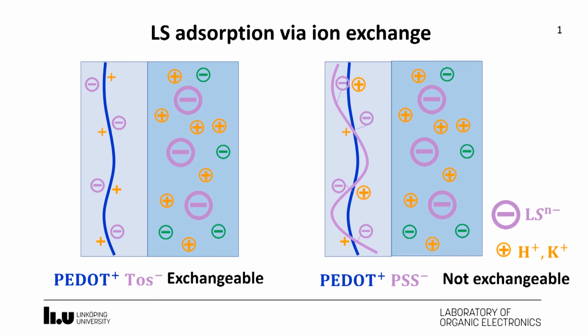at the PEDOT:TOS electrode, when the tosylate ion moves out, there will be an attraction force that attracts lignin sulfonate molecules into the polymer, while in the case of PEDOT:PSS, as PSS is immobile and carries a negative charge, it will repel lignin sulfonate out. There will be less lignin sulfonate adsorbed.